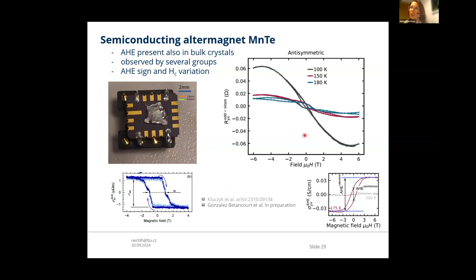This is all fine, but similar to us, the team of Kluczyk et al. also observe that the effect is present, but you see that the sign of the effect is opposite to the sign in the thin films. And also that the coercivity varies significantly between the samples.